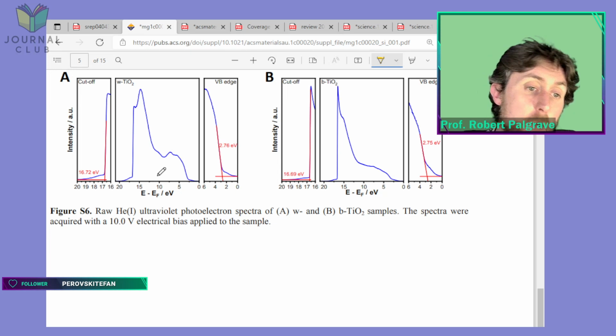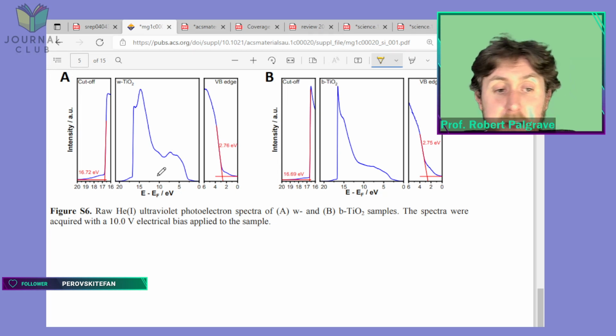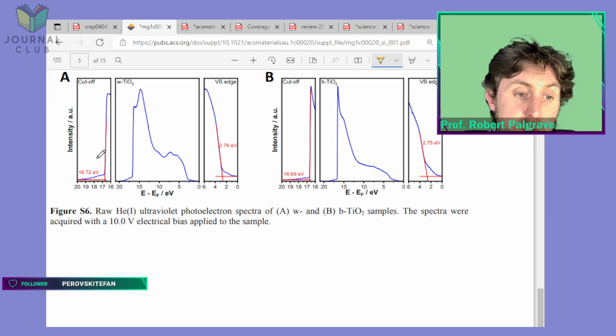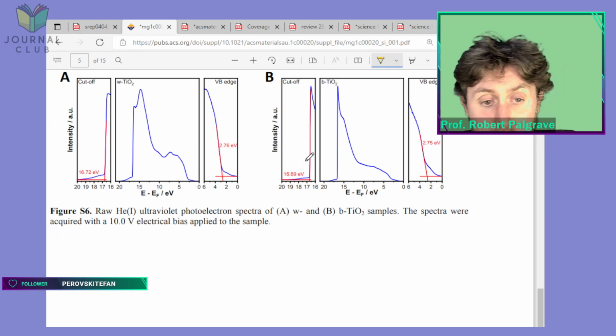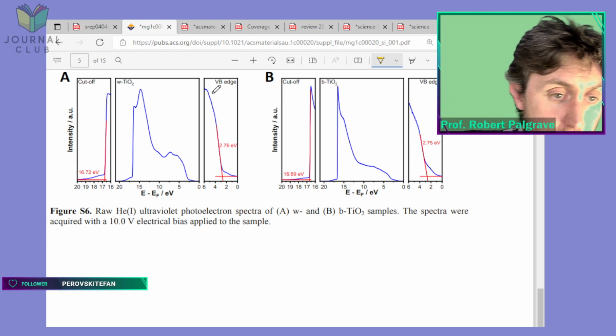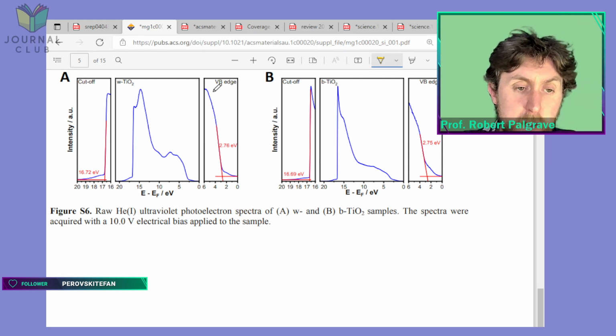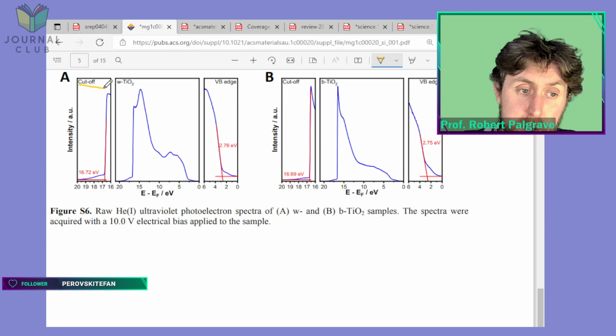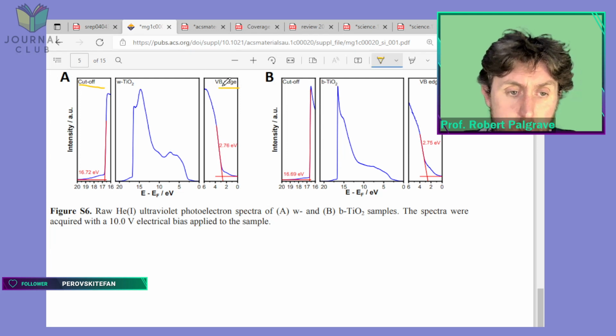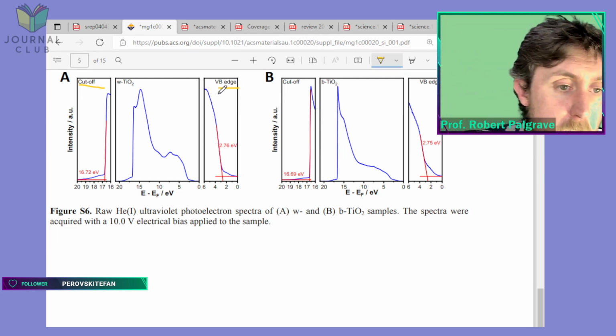So this is another way to try to understand the outermost electrons of the material. Here they're actually using a method to work out what's called the work function of the material. They're looking at these two cutoffs: a low kinetic energy cutoff, high binding energy cutoff, and a low binding energy, high kinetic energy cutoff at the valence band edge.